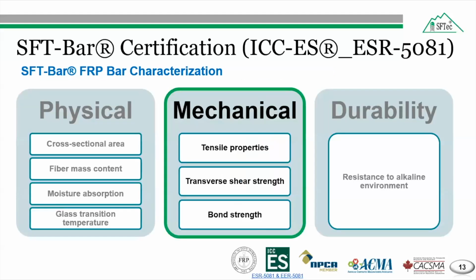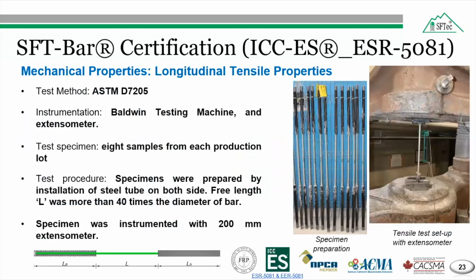Now coming to the mechanical properties, which include tensile properties, transverse shear strength, and bond strength through pull-out test. So the tensile properties, or we can say the longitudinal tensile properties of FRP specimens, were tested in accordance with D7205, and the instruments used in this test were a Baldwin testing machine and an extensometer for displacement recording. The test specimen was prepared by installation of steel tubes on both sides of the FRP sample using expansive cement, and the length of the steel tube was around 40 times the diameter of the bar.